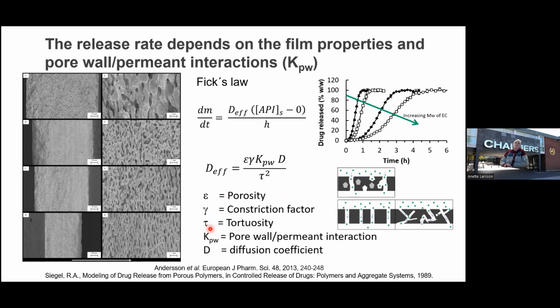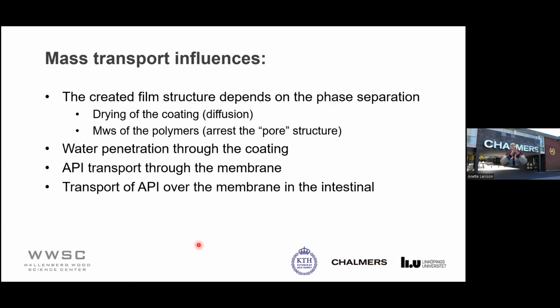And the first three factors here depend directly on the film, whereas the last one here is the interactions between the active substance and the wall in the pore, and of course the diffusion coefficient of the drug as well. So if I try to summarize this part, the mass transport depends on the phase separation, the structure we got, and that depends on the drying speed and also the molecular weights of the polymers, since they arrest the pore structure in different ways.